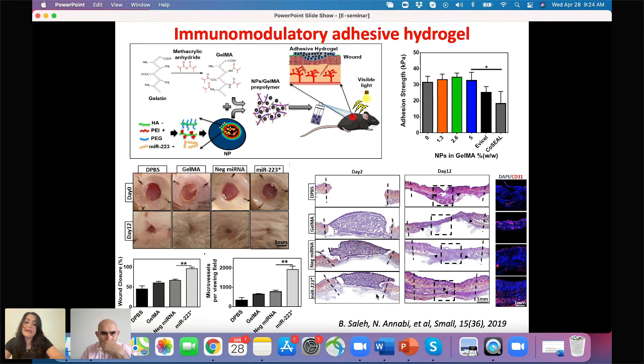And if you look at the H&E staining, you see that for the group containing miRNA, we have better healing, better wound healing over time. And also based on immunostaining, we observe a higher degree of vascularization as we incorporate this miRNA inside our bioadhesive hydrogel. Therefore, by combining miRNA nanoparticles in a bioadhesive biomaterial, you can control the immune response toward regeneration and vascularization. So this was one modification that we did in our adhesive biomaterials.